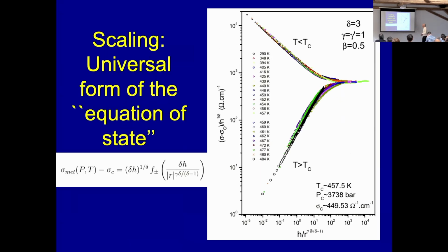And we were even able, and I'm actually pretty proud of that, to scale the whole set of data onto the universal equation of state that you would expect from an Ising model. And you know, as far as data collapses go, I know you can still make a lot of data collapses when you want them to collapse, but this is not so bad.